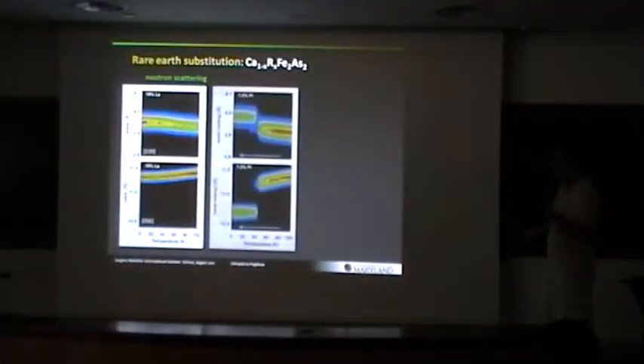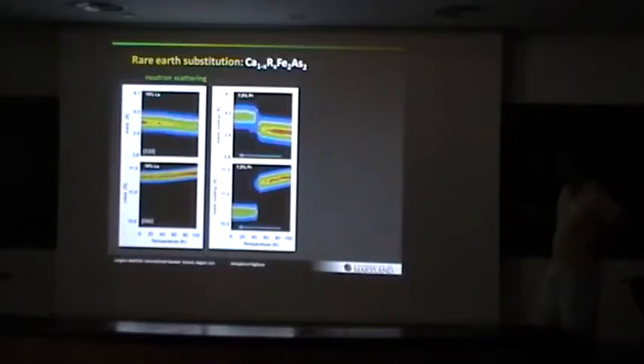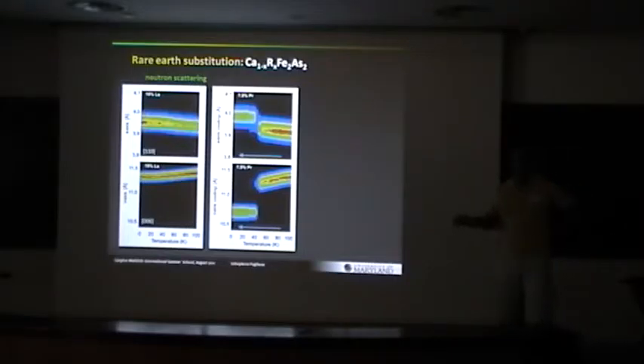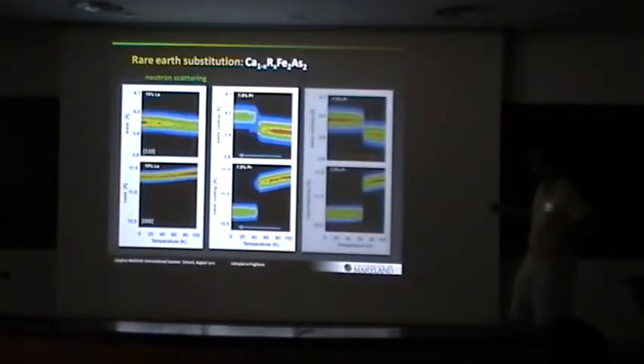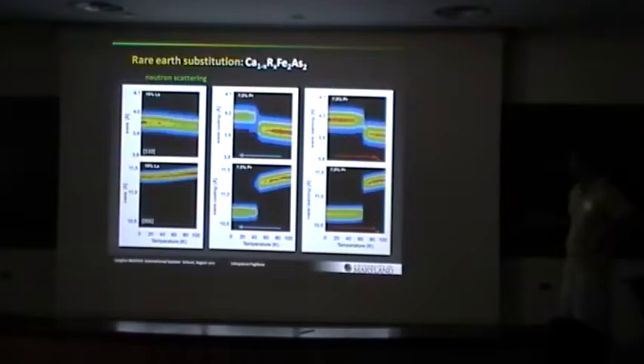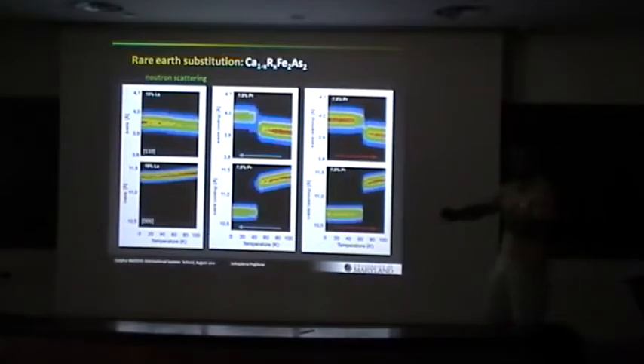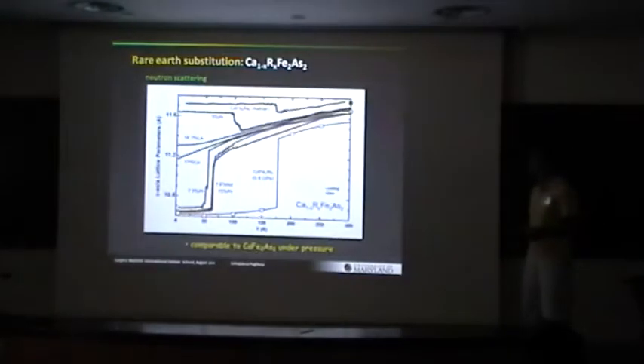Okay, so here's some neutron scattering data. Sorry, show this first. This is with lanthanum substitution, which, as I said, does not cause a shrinkage of the c-axis. And this is a-axis and c-axis versus temperature. Nothing funny happens. But when we put praseodymium in, you see that there's this structural transition. And again, this is roughly 10% or so of the unit cell. So this behavior looks very much like calcium 122 under pressure. And this is cooling in temperature. If we increase the temperature, it's the same thing, but it's quite hysteretic. This is 40 Kelvin, this is 60 Kelvin. So there's a big hysteresis. And these are ambient pressure measurements.